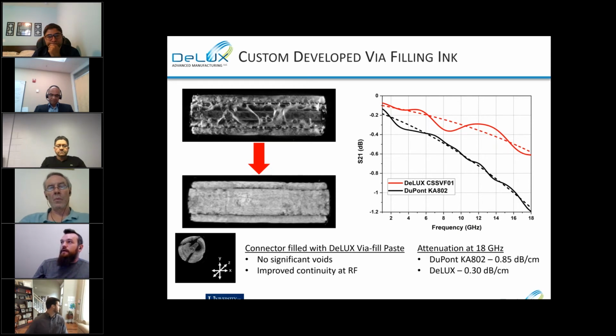And you can see here, same geometry of the connector, same build process, etc. And here's a CT scan of our printed conductors. You can see very low void content, excellent conductivity. And so we're able to drive that performance back up to where we deem acceptable. And so we're able to get printed connectors with attenuation constants as low as 0.3 dB per centimeter, which we find to be pretty acceptable for most application spaces.